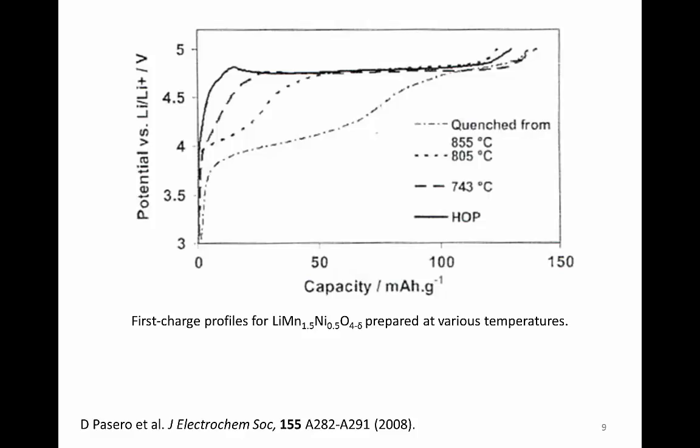And this is because we now have different redox couples associated with the process. So the manganese oxidation state has changed from +4 to +3, and that is then giving us a different redox couple in the process. And so that is really quite bad news for the battery, because you want to have a constant voltage during charge and discharge.